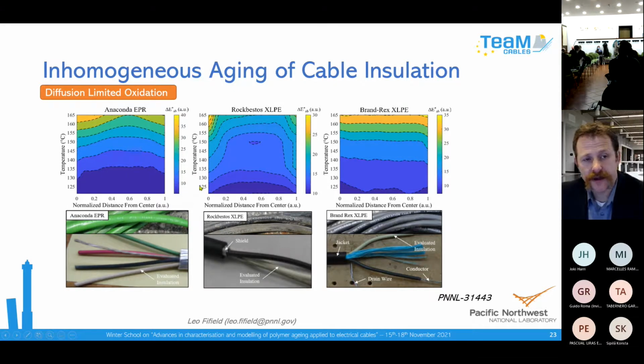Similar results were observed for this XLPE, but we observed that this kind of behavior is material dependent. In this Brand Rex XLPE, even at the highest temperatures, we saw more homogeneous aging throughout the thickness. So that's been a common theme when we've tried to look at these knowledge gaps: we can't paint with a broad brush the behavior of all materials and say all cable insulation will behave a certain way. As you might expect, if you look at what they're made out of, these different formulations have different chemistry, and they're going to behave differently when they're exposed to environmental stresses over time.